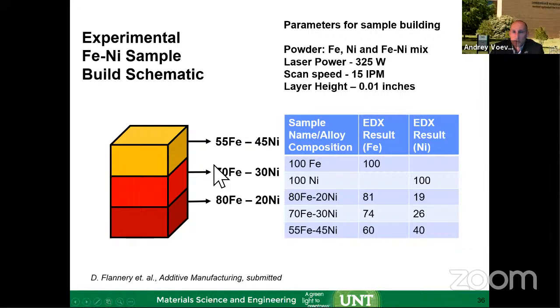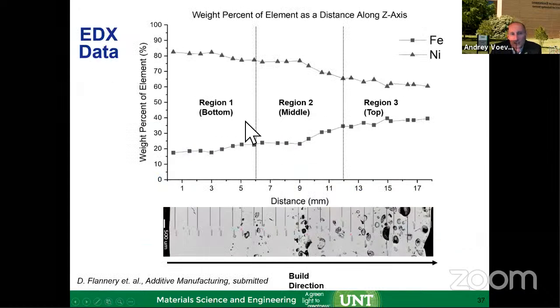We also did post-build EDX analysis to actually correlate that we're feeding the powders with this composition. That's what we see in iron, and that's what we see in the nickel in terms of the production after it's done. So that's looking at the element distribution. After we took the sample and cross-section, that was the bottom, that was the top. As we go from the bottom to the top, we're increasing the iron and dropping the nickel because we are changing the powder feeding.